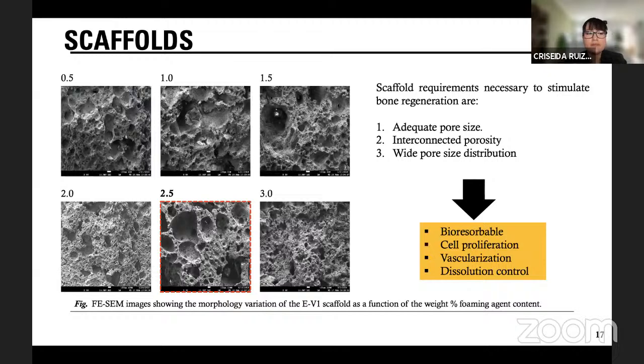Then the bioactive glass powders were obtained and mixed with beta-tricalcium phosphate powders in variable amounts, with different reagent ratios, until obtaining scaffolds with a wide pore size distribution, so bone regeneration could occur in long bones such as the tibia, femur, or fibula. They had a wide pore size distribution and interconnected porosity. This aspect allowed resorbability, cell proliferation, vascularization, and better control of the scaffold dissolution.